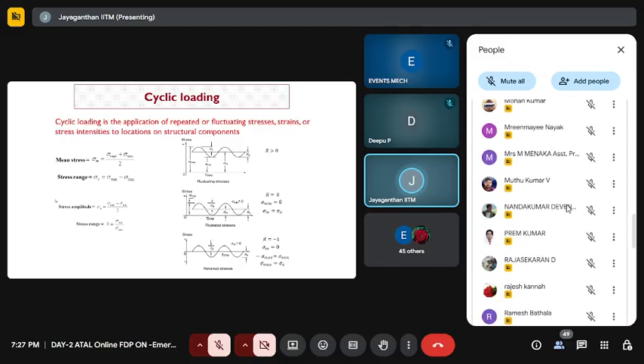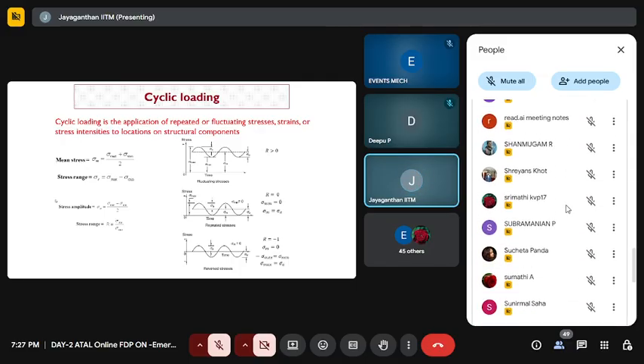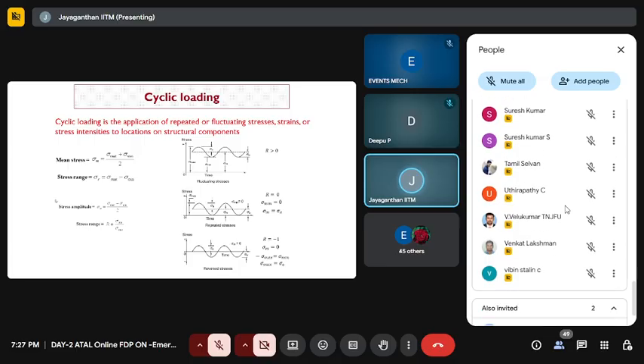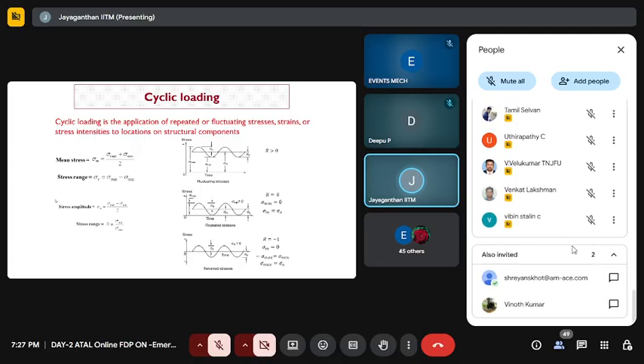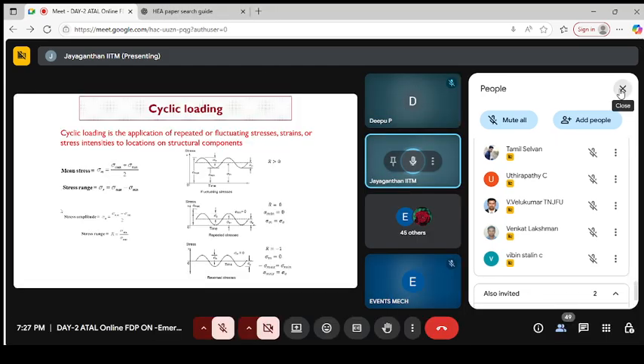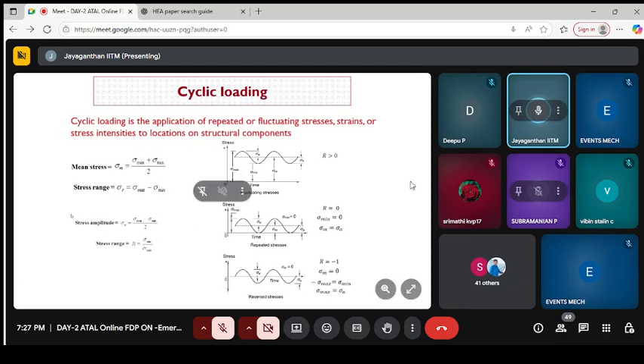Rather, we want to look at the loading pattern of the parts. The top one: when you do fatigue testing of any material, you need to have an understanding of all these terms: mean stress, stress range, stress amplitude, stress ratio R. Look at the different loading patterns. If it happens to be fluctuating stress, R is greater than 0. If it happens to be repeated stress, look at R equal to 0. Having defined the stress range, sigma minimum to sigma max, if it happens to be reverse stress, look at the R value. We do fatigue testing of the sample with respect to the R value that is kept.